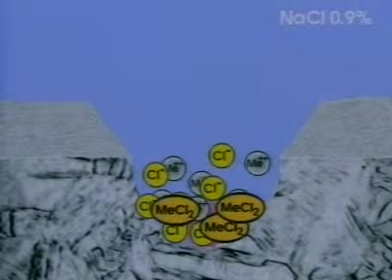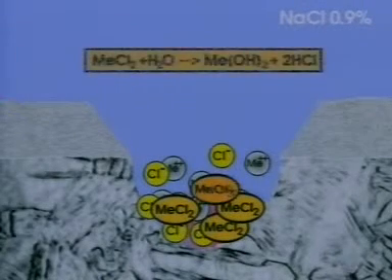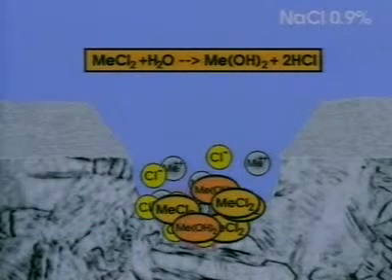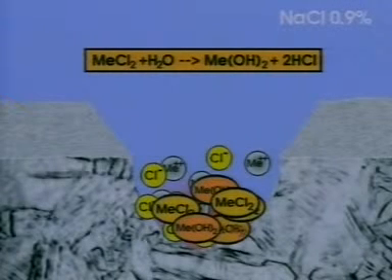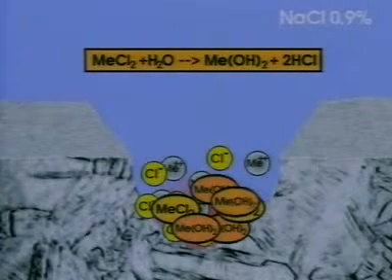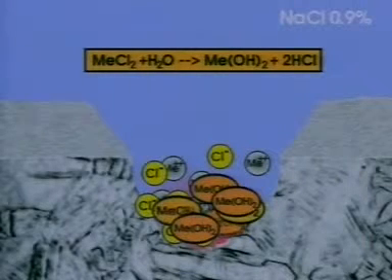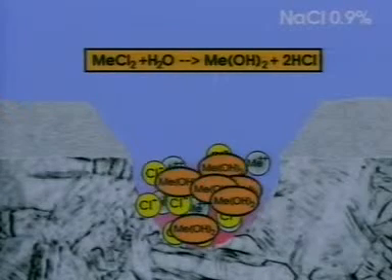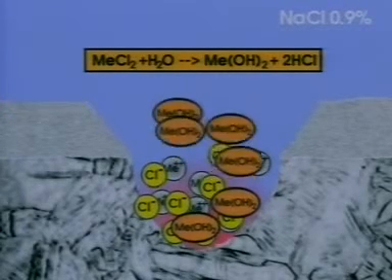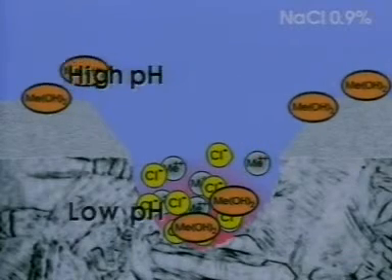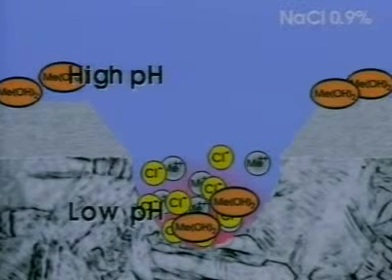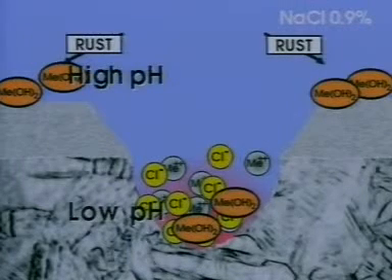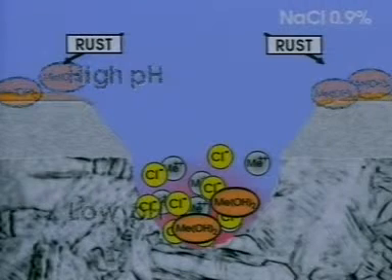Unfortunately, metal chloride molecules hydrolyze at higher concentrations, producing an acid chloride solution. The production of hydrochloric acid lowers the pH which holds the metal hydroxide molecules in solution. This aggravates the situation. The passive film does not form well at low pH. At this stage, a stable pit forms. Unfortunately, iron, the major component of stainless steel, hydrolyzes very easily, which explains its susceptibility to pitting attack.